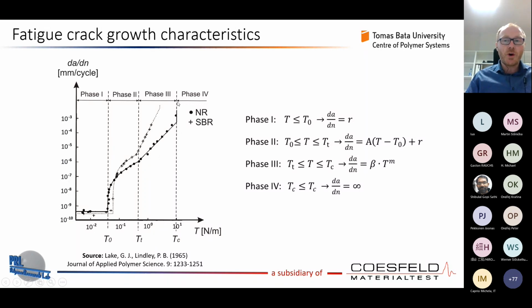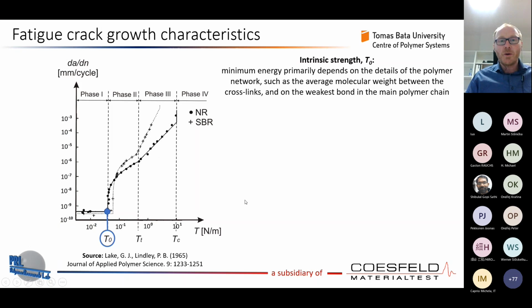And then we have phase 4, which is non-stable, unstable crack propagation, very close to TC, the critical tearing energy, and over or close to the critical tearing energy. That's an energy where the crack is not possible to stop anymore. So let's go into more detail in this characteristic.